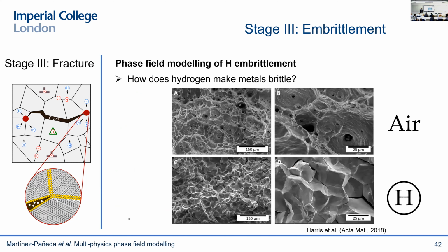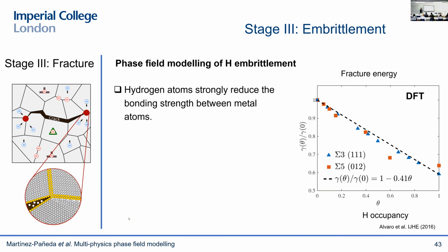But anyway, let me tell you what I think is the key hydrogen degradation function. And if you try to come up with a mechanistic interpretation of this problem, then I think the key question you need to answer is, how does hydrogen make metals brittle? How can it be that a metal that fails in a very ductile manner, as you can see here through micro-void cracking mechanisms, suddenly in the presence of hydrogen fails in a very brittle fashion with cracks originating along the grain boundaries? And to me, there are three things that are key to understand this.